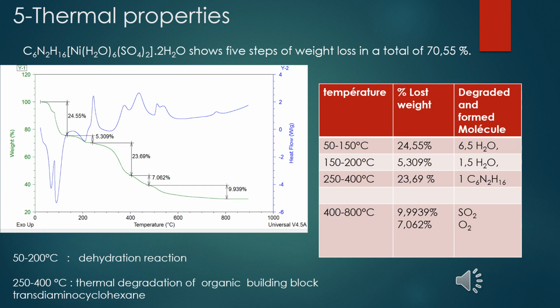The thermal analysis shows that this compound loses coordinated and free water molecules between 50 and 200 degrees Celsius. The thermal degradation of the organic building block trans-diaminocyclohexane takes place between 250 and 400 degrees Celsius.